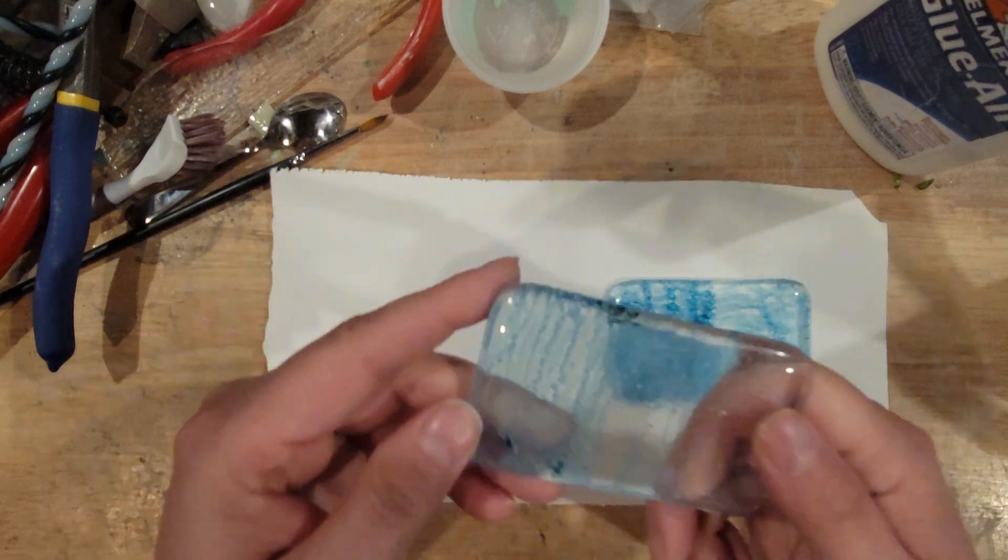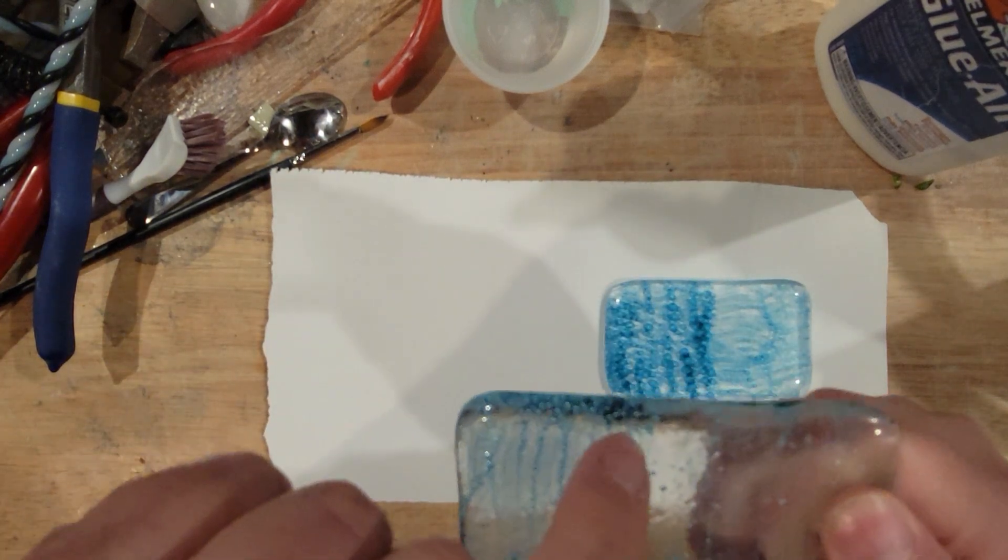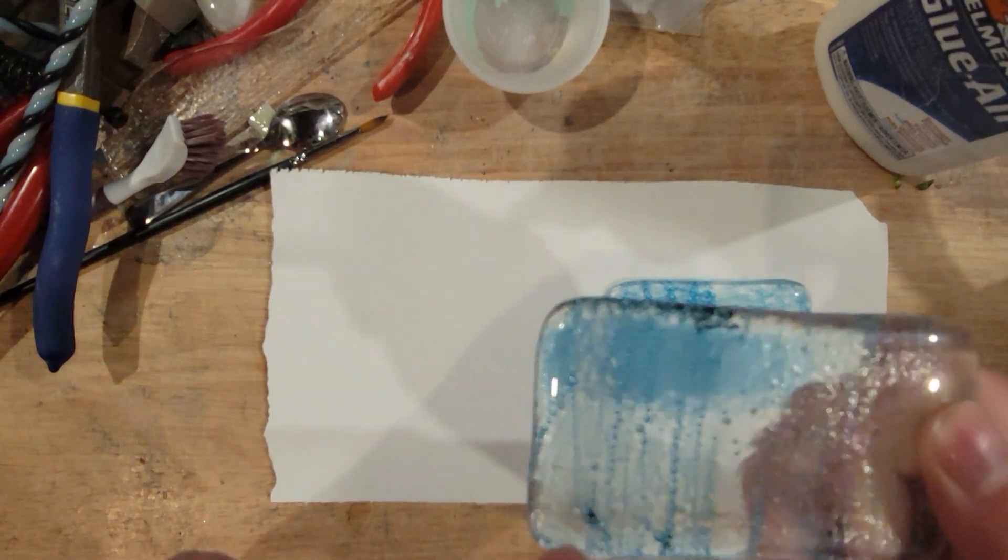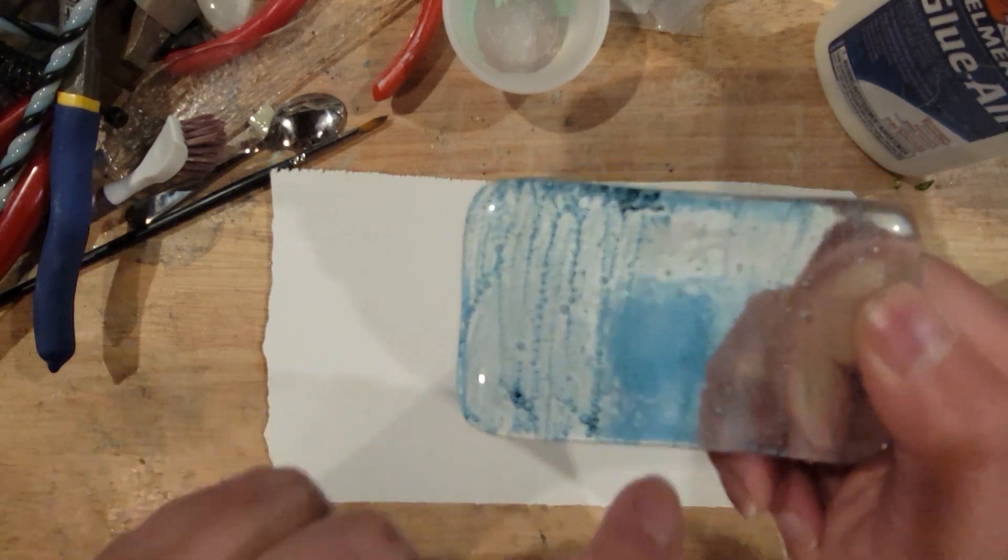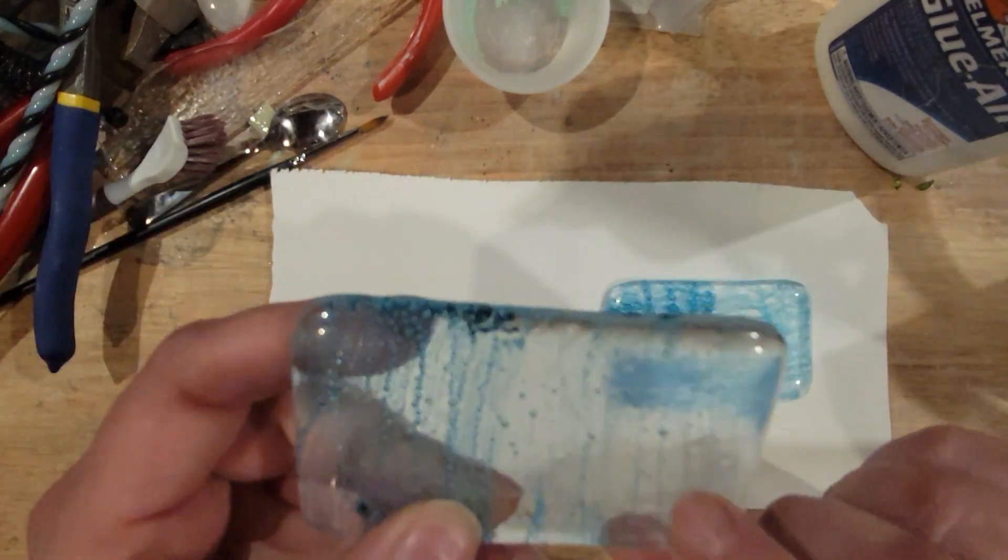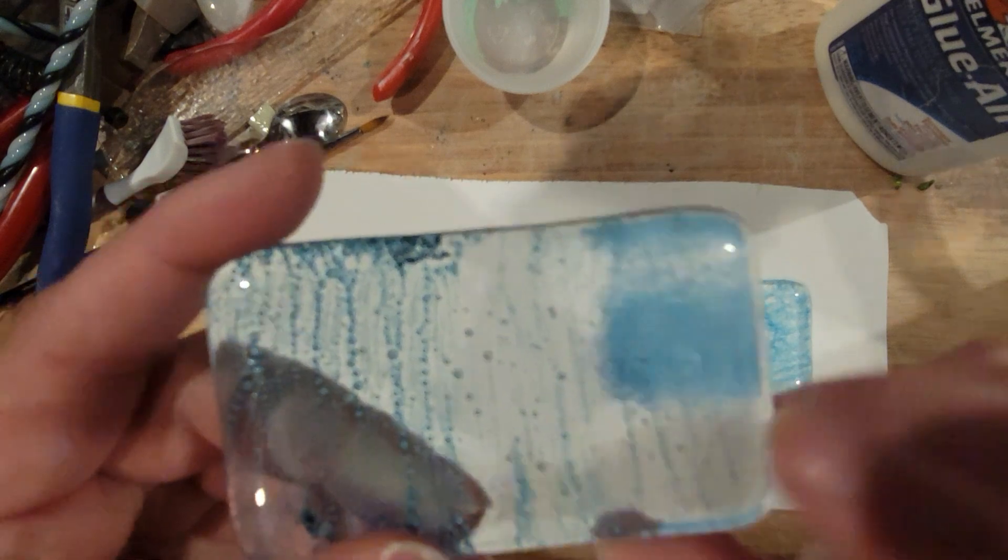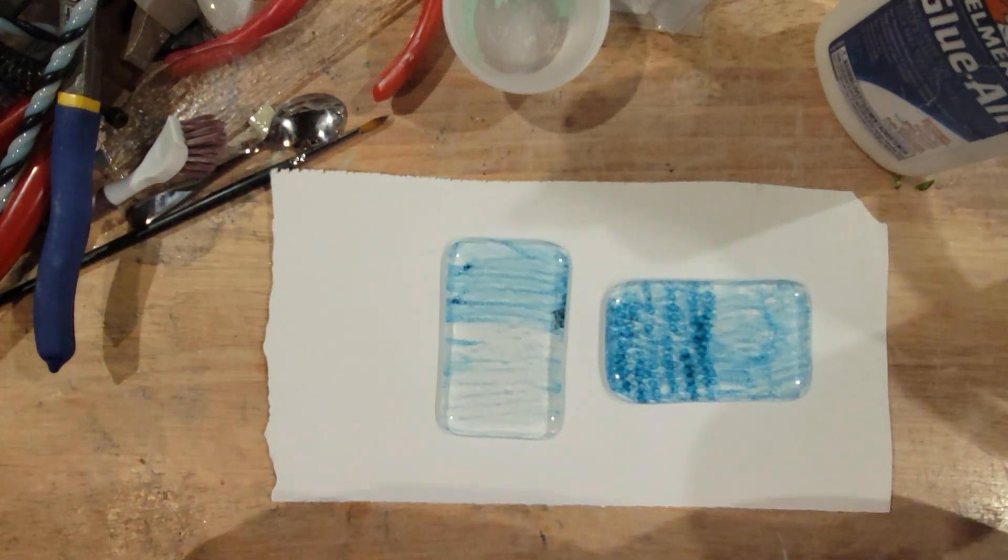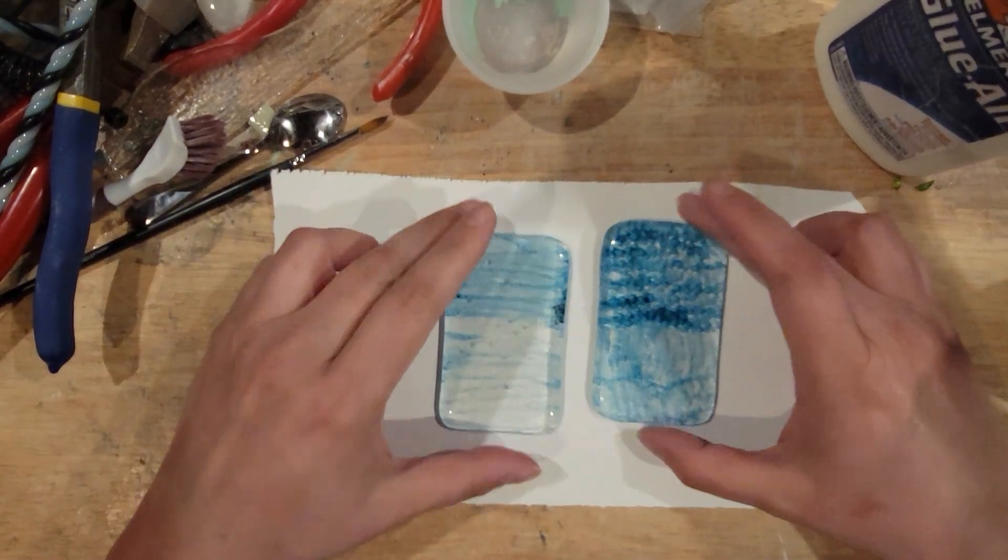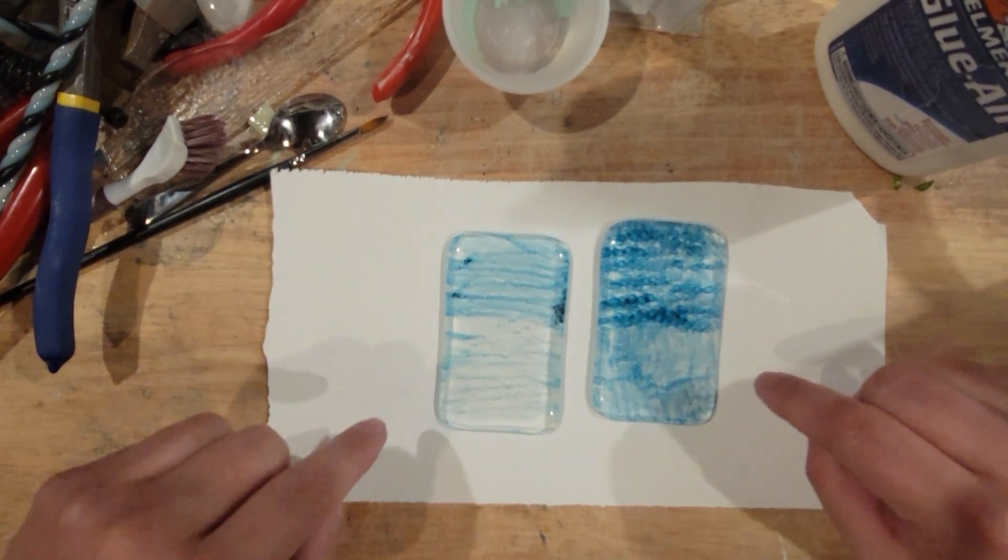And this is copper carbonate. And I think it's kind of interesting that again, it didn't oxidize everywhere. But where it was lightly applied, it really didn't bubble. You have to apply it pretty thick. I mean, there we go. Heavier brush, fuller coverage, lighter strokes.